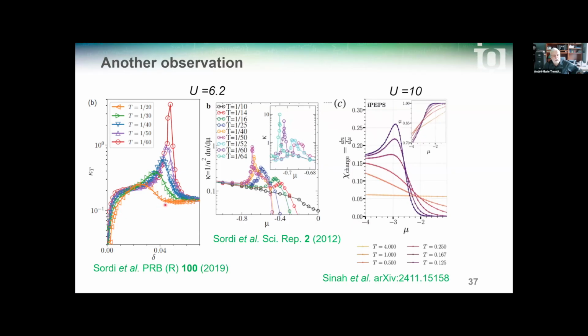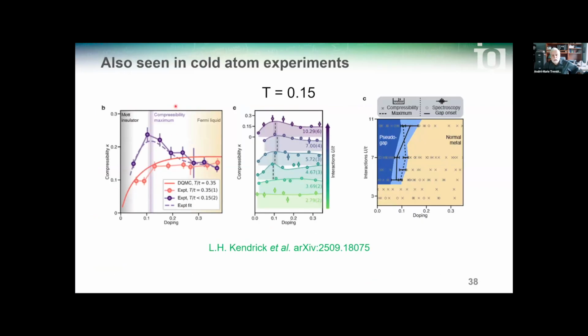On the left here, the results for the compressibility are plotted as a function of density. There is a recent preprint from Harvard that observed this phenomenon in cold atom experiments. You can see on the left how the maximum of compressibility as a function of temperature evolves as temperature is decreased. So this is compressibility and doping. And you can see in the middle plot how at fixed temperature, the doping where the compressibility maximum occurs changes with increasing interactions. This gives on the right a phase diagram where the pseudogap is separated from the normal metal by a compressibility maximum.